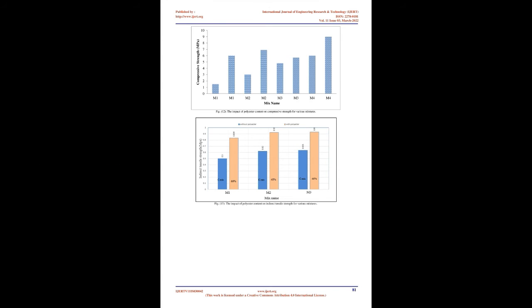Figure 4 demonstrates the mix name and the corresponding compressive strength at 7 days and 28 days. The figure indicates that the compressive strength at 7 days is 71% to 80% of the strength at 28 days. Fig. 5 demonstrates the impact of cement content on compressive strength for all different mixes.